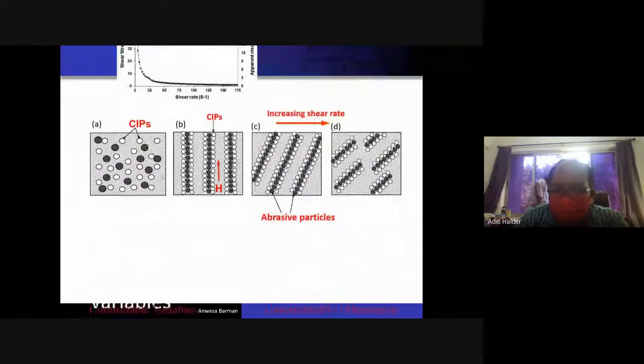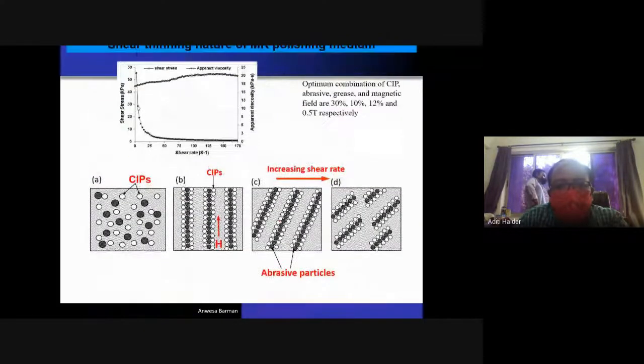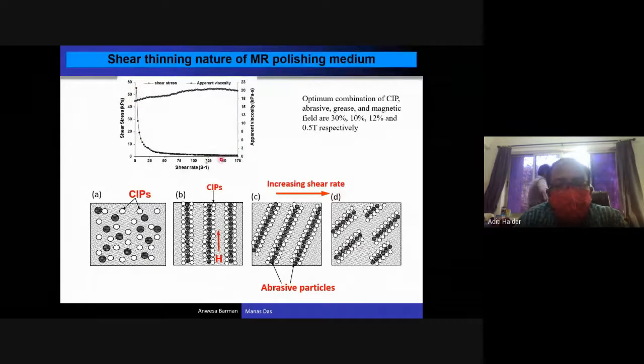Now you can see here that the viscosity of this MR fluid is reducing. The viscosity of this MR fluid reduces with the shear rate. So this MR polishing fluid is a shear thinning fluid. As viscosity reduces with shear rate, it is a non-Newtonian fluid, specifically a shear thinning fluid.